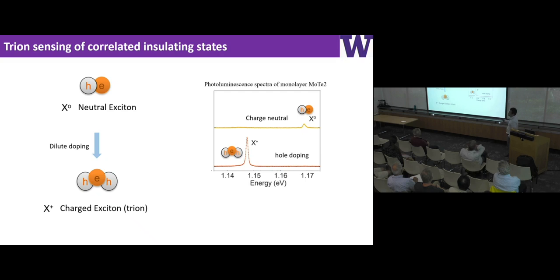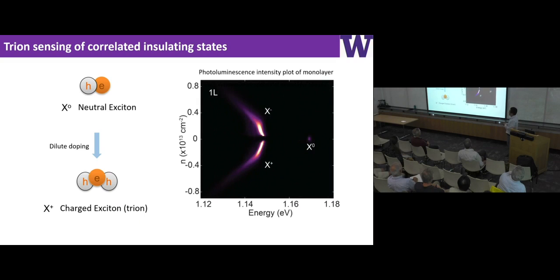Here's a typical photoluminescence spectrum from a monolayer MoTe2. You see we have a neutral exciton emission, and we have a charged exciton emission. You can see there's an energy separation between these two, so you can clearly tell there's trion formation. If I continuously tune my carrier density on this vertical axis, what I show here is the luminescence intensity plot from a monolayer. You can see a neutral exciton at charge neutrality. Then you see the trion appears. The intensity is continuously tuned.